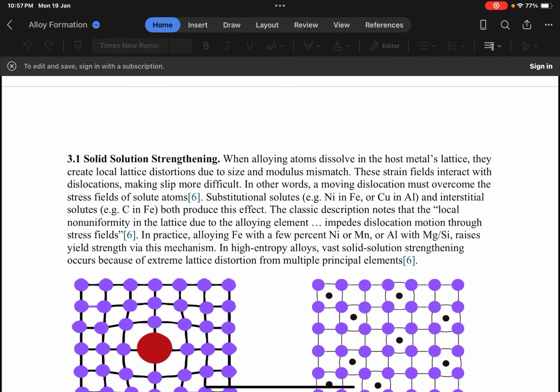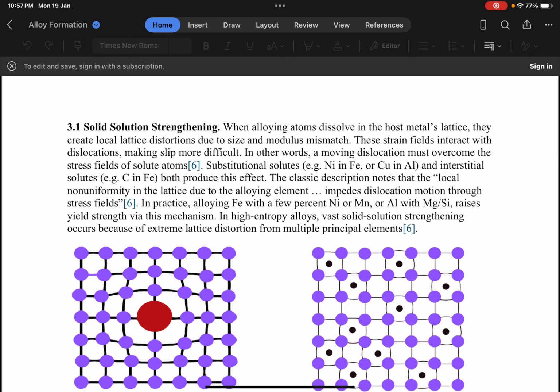First of all, I will talk about solid solution strengthening. When alloying atoms dissolve in the host metal lattice, they create local lattice distortions due to size and modulus mismatch. These strain fields interact with the stress field of dislocations. Substitutional solutes, nickel in iron or copper in aluminium, and interstitial solutes, for example carbon in iron, both produce this effect. The classic description notes that the local non-uniformity in the lattice due to the alloying element impedes dislocation motion through stress fields. In practice, alloying iron with a few percent nickel or manganese, or aluminium with magnesium and silicon, raises yield strength via this mechanism.